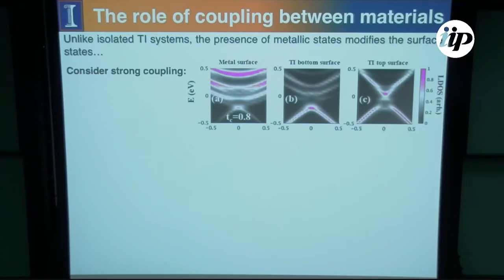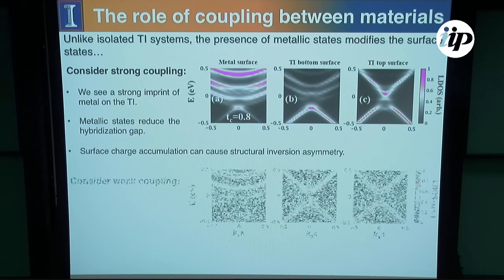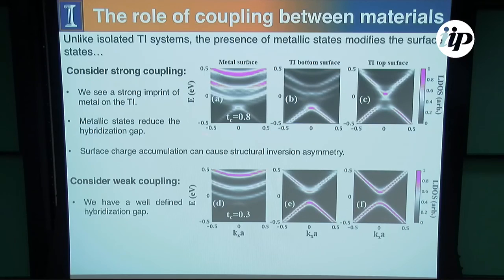One of the things that I thought was particularly interesting: when we moved away from this analytic model and started calculating what was really going on within the system, as we started adding in disorder, this interesting result came out. This is what happens when we look at coupling between the topological insulator and the superconductor. We never really thought too much about how the bands changed, but if you consider strong coupling and compare it to weak coupling, you can see that the bands for the topological insulator are significantly changed by the much stronger coupling between the topological insulator and the superconductor.